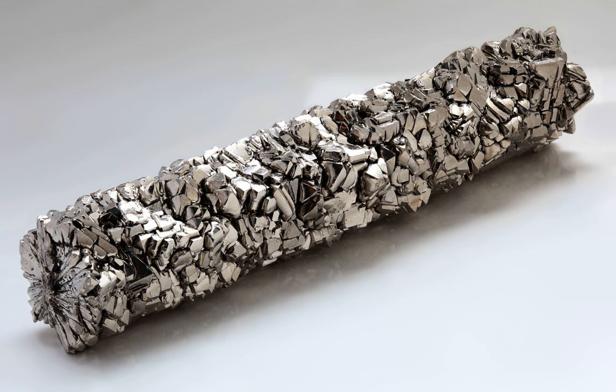Applications. Titanium powder is manufactured using a flow production process known as the Armstrong process that is similar to the batch production Hunter process. A stream of titanium tetrachloride gas is added to a stream of molten sodium metal. The products, sodium chloride salt and titanium particles, are filtered from the extra sodium. Titanium is then separated from the salt by water washing. Both sodium and chlorine are recycled to produce and process more titanium tetrachloride.